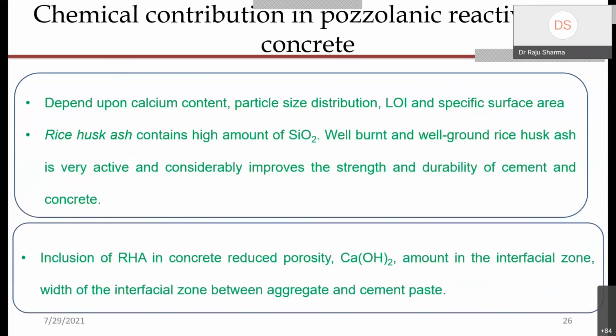Now, depending upon calcium content, particle size distribution, loss on ignition, and specific surface area, right? If you say the rice husk ash contains a high amount of SiO2. So well burnt and well ground rice husk ash is very active and considerably improves the strength and durability of cement and concrete. Here the point is well burnt and well ground rice husk ash. This is the game where the product changes its behavior globally, right? So well burnt and well ground rice husk ash. We will see in the next slides how these two factors affect the performance of the final product. So it is very active and improves the strength significantly.